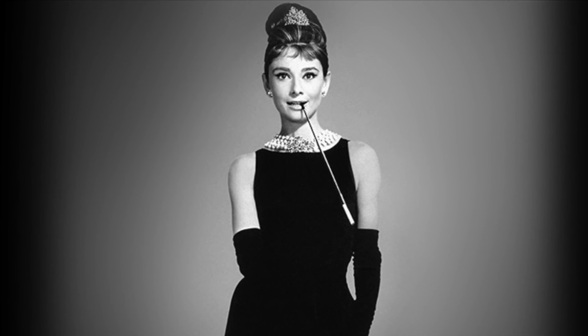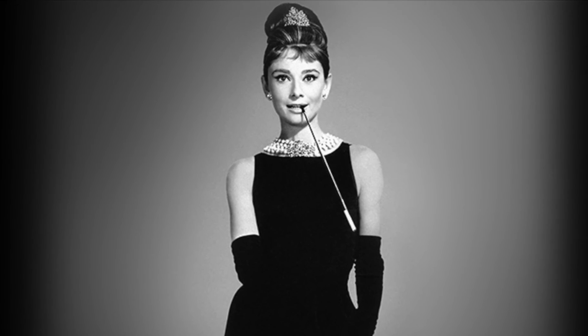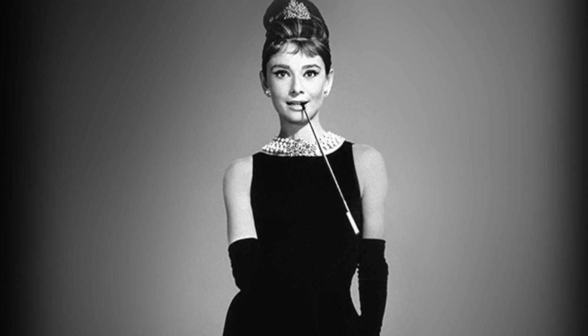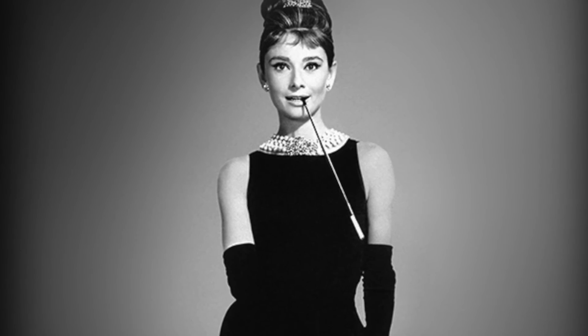After exposing the coating to space qualification testing, the results showed no changes in hemispherical reflectance value. The consistency and durability of Vantablack, due to the unique properties of CNTs, is a major indication that a material can successfully be utilized in future space observation applications. Although some were hopeful, Vantablack will unfortunately not be made into clothing or used for everyday purposes. No little nano black dress, or at least not yet.